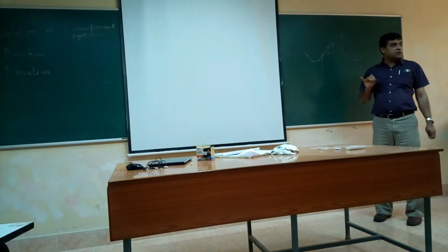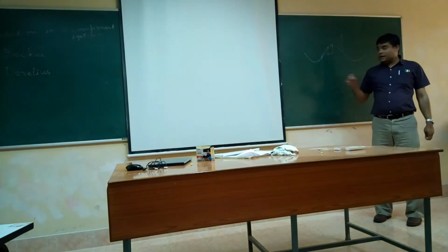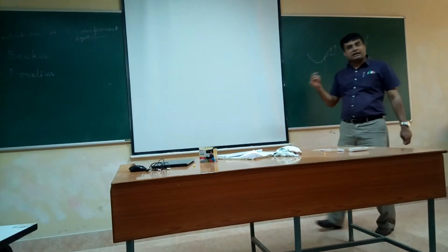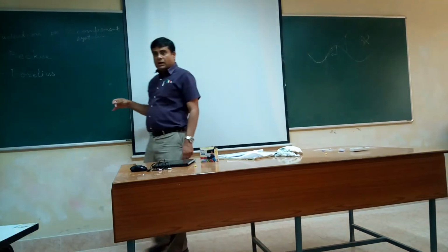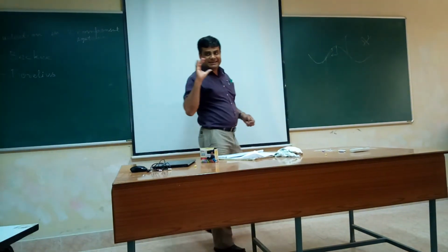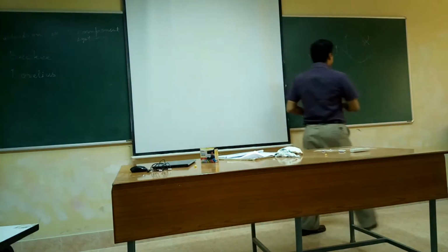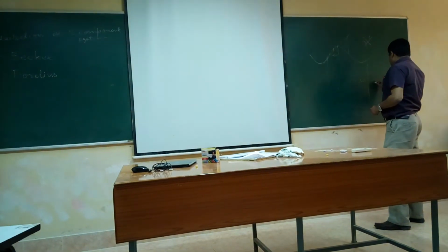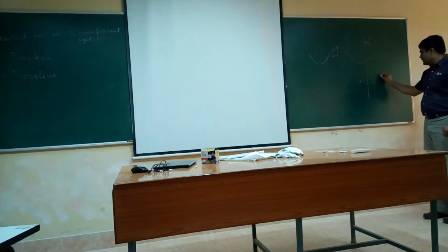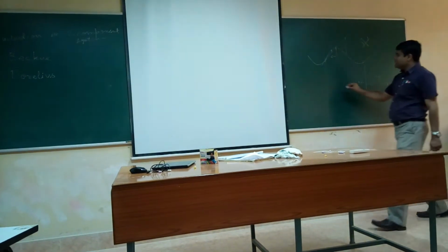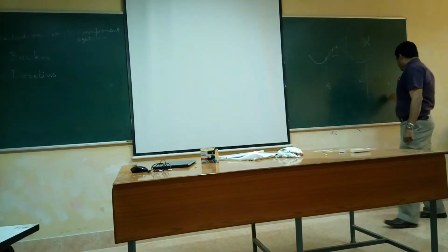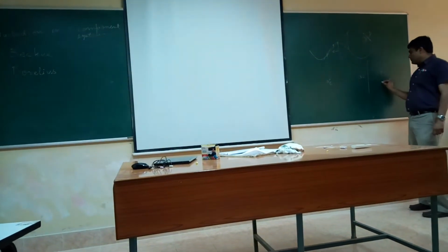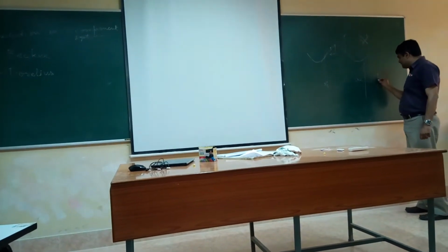But for the Borelius model, the gamma term, the interfacial energy, was ignored. The only thing that came into the picture was delta G. If we plot delta G, we get this type of curve. This is that Xc where delta G will be 0, but there is some other X star where it is maximum.